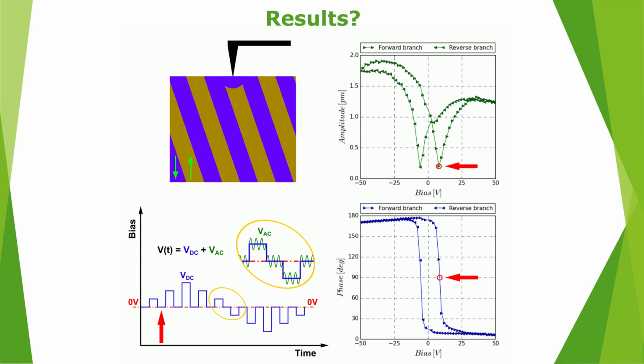The last experiment, switching spectroscopy piezoresponse force microscopy, monitors the change in piezo response while the polarization underneath the tip is gradually switched by voltage pulses with increasing amplitude. This method yields characteristic hysteresis loops which contain a lot of information about the local switching dynamics of the relaxors.